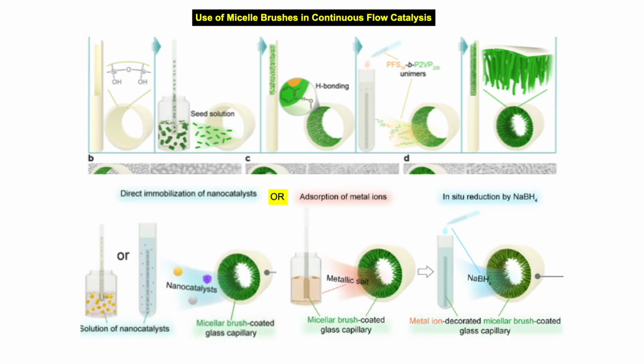So you can take a surface or a capillary and add the seeds to the capillary so they attach to the surface. You can then add polymer so it grows from the surface, giving you a brush layer on the interior of the capillary. You can then add nanoparticles which stick to the brush layer.